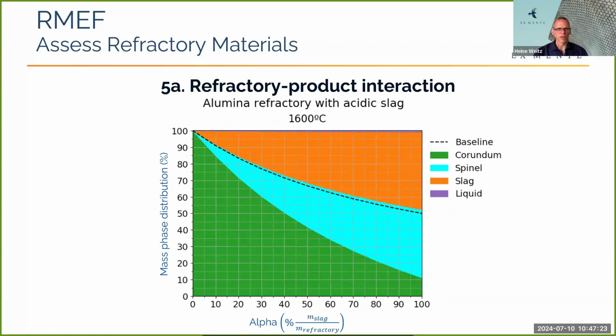Now, this is just a simple example of alumina refractory in contact with an acidic slag. So on the far left, we've only got the alumina refractory, and that is a corundum phase. And as we add slag to that material, you can see that the corundum slowly but surely changes to a spinel. And on the far right, we've got mostly spinel with some corundum. And you can see, because your solid phases are above this dotted line, it means that you end up with just as much or more solid material than you started off with in your calculation. So at least from a melting point of view, this refractory material is fine at this temperature, but you do get a phase change, which one also needs to think about if there is a volume disparity between the phases, which might cause the refractory to spoil.